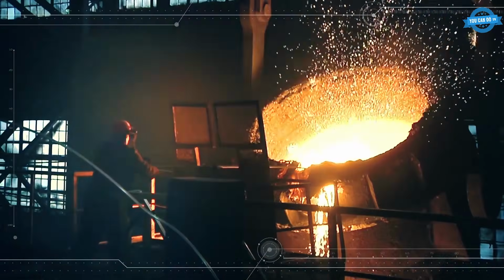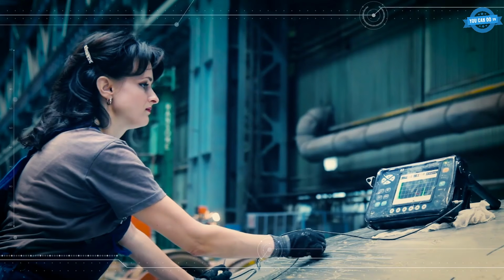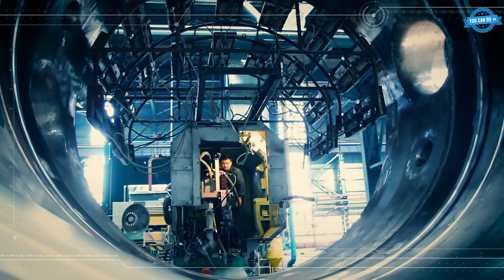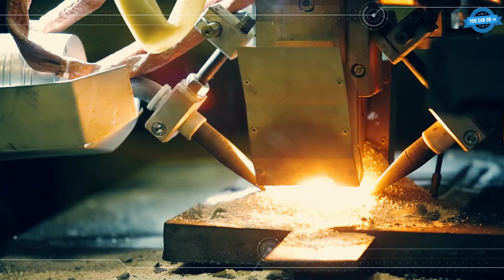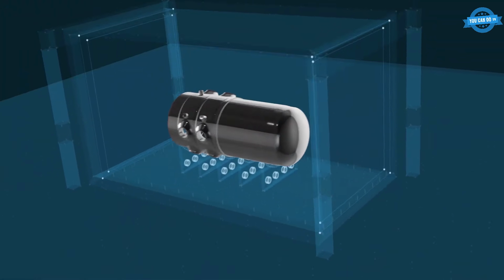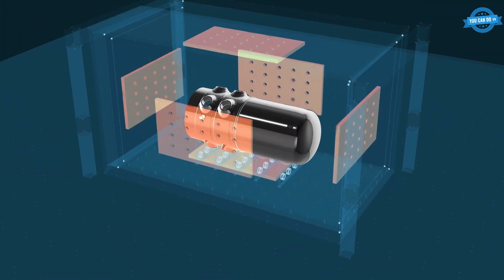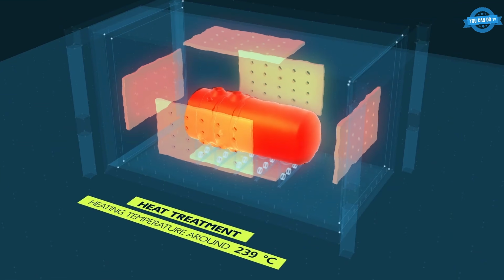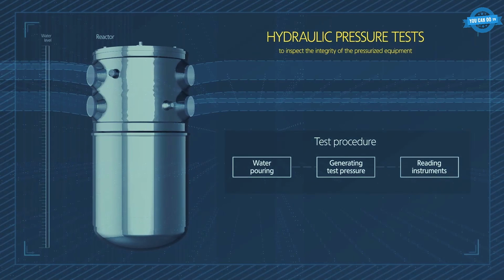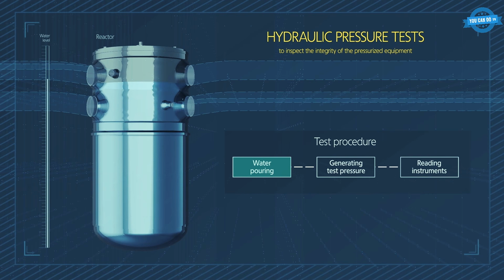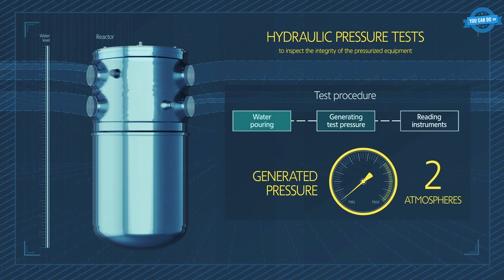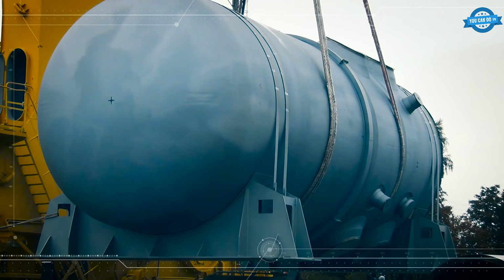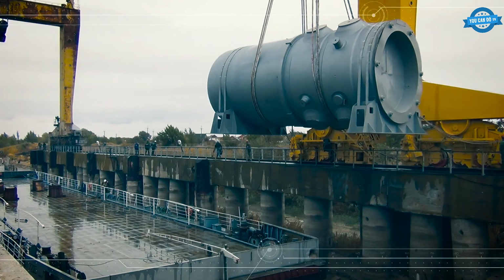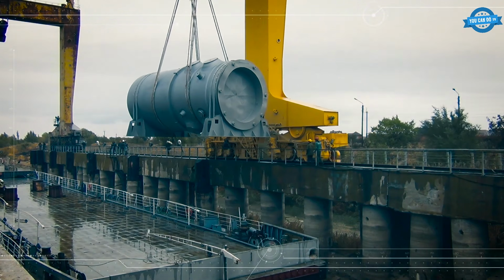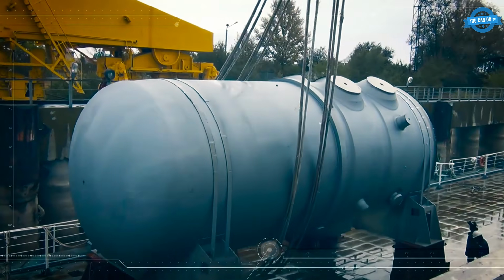Every shell ring is forged, machined, ultrasonically tested for internal flaws, and welded to the next one with automated submerged arc welding. The finished vessel gets heat-treated inside a furnace big enough to swallow it whole, X-rayed at every weld, then hydraulically pressure-tested. Decades of reactor operation ultimately depend on every one of those welds behaving exactly as designed. After all that, it ships by heavy-duty trailer and barge, because at that size, no other transport method exists.